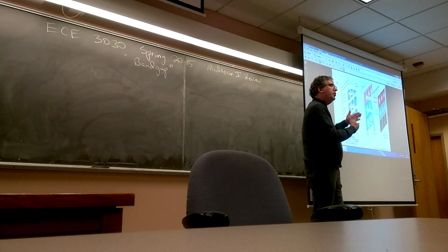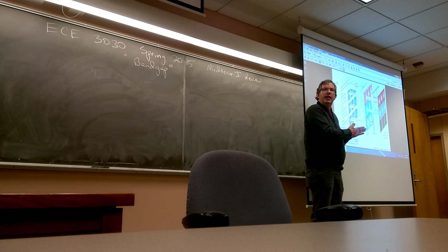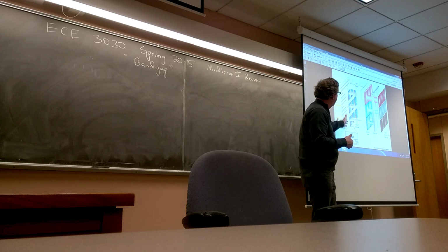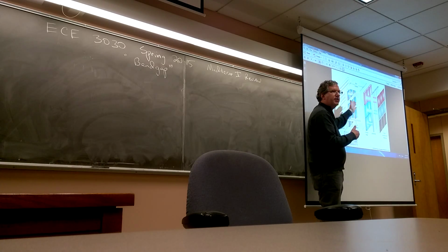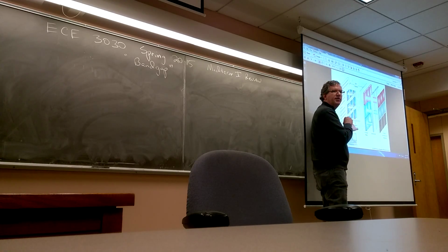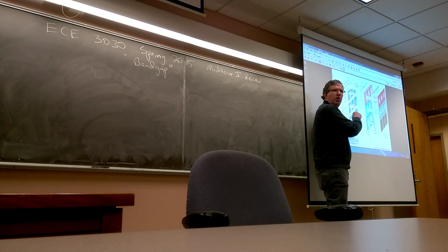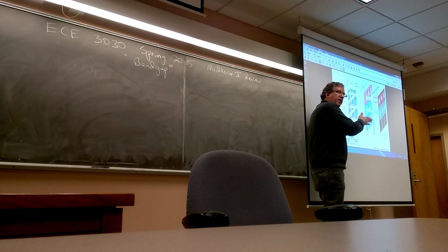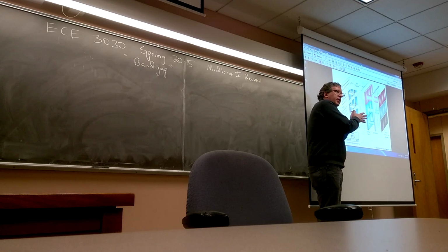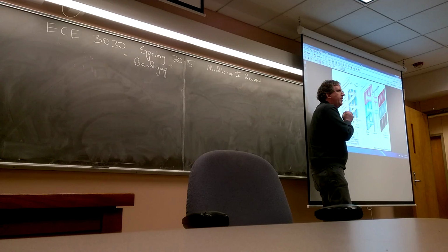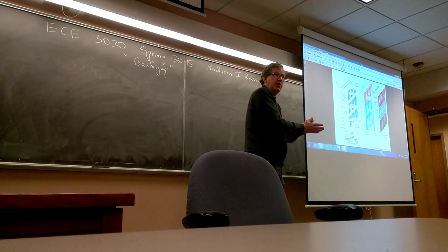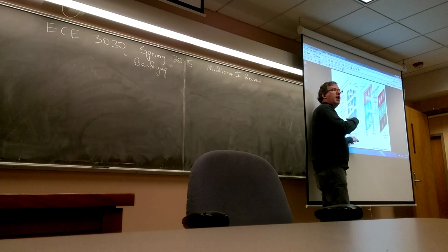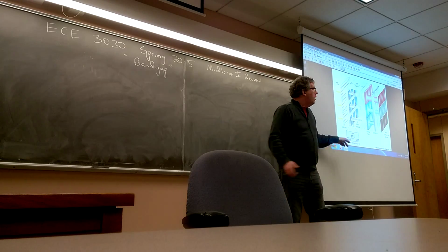And maybe I came in judiciously with a high power laser, and without killing the glass or hurting other parts, I just delivered a little bit of heat pulse and caused that locality of silicon to melt. And then I give it enough time, it slowly condenses and recrystallizes like that arc weld, and maybe it'll manifest as more of a polycrystalline material. So I just gave it temperature and time. Those are two key ingredients. And so now I got a polycrystalline, so now I got a higher mobility.